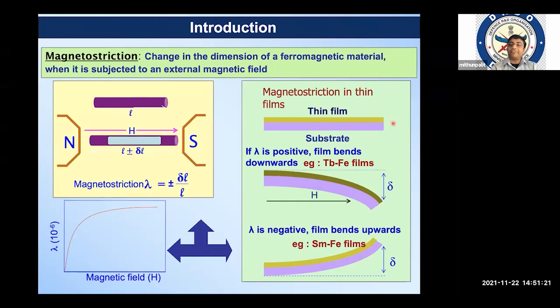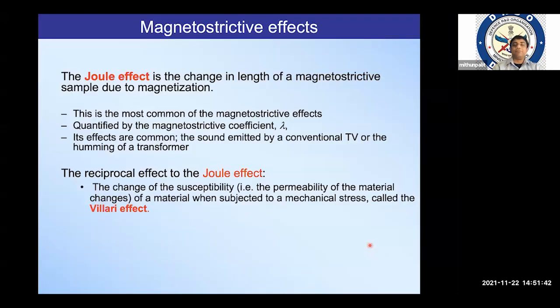For example, in this thin film, the top layer is magnetically active, and the bottom layer is magnetically inert. So if you have a positive magnetostrictive material, the film bends downwards, and because the bottom layer is inert, it will try to accommodate the stress generated in this layer, so it will try to bend downwards. In case of a negative magnetostrictive material, the film will bend upward.